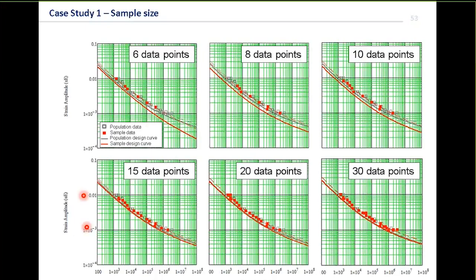It isn't until we start to get to 15 points, which is typical ASTM ISO territory, that we've got a good chance that we get a fairly even distribution that we're looking for. But at 15 data points, unless it's perfect, our design curve is still quite a high safety margin off it. In fact, what we find is typically we need 20 to 30 points before we end up with this economic optimum. So at 15 points, we could get there, providing it's evenly distributed, but usually it's not even.